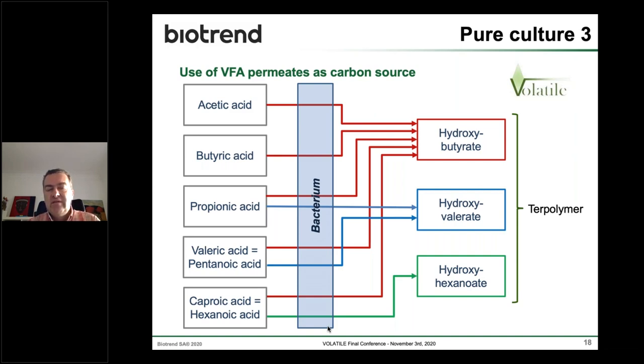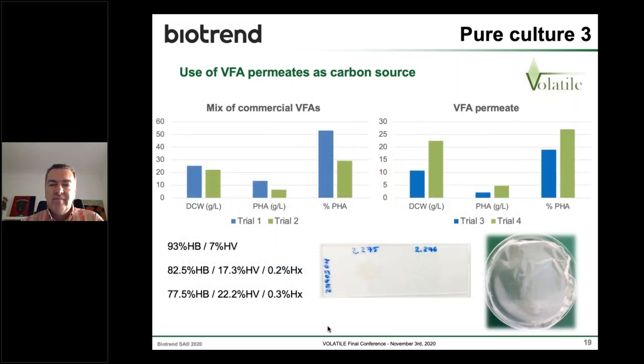So here we come to this goal of having a more diverse structure and properties of the polymer in order to try to render it useful for a wider range of possible applications. So we started during volatile to simulate these mixed volatile fatty acids, and we were successful in producing PHA and accumulating PHA intracellularly, and actually detecting three different monomers in the polymer by GCMS, confirmed by NMR later on.